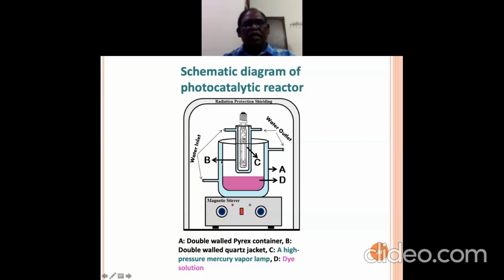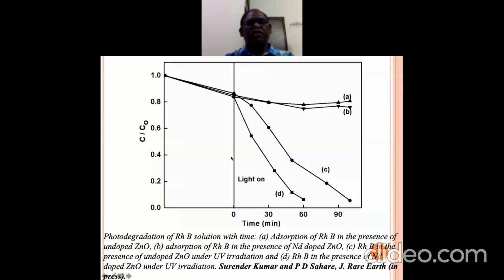So in this reactor, this is a rhodamine B dye solution, and this is UV light, and this is made of quartz because glass absorbs it. And therefore we studied with time, and you can see that within 1 hour or so, this colored solution becomes colorless, meaning the dye is disintegrated over there.